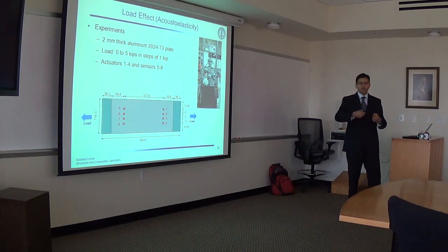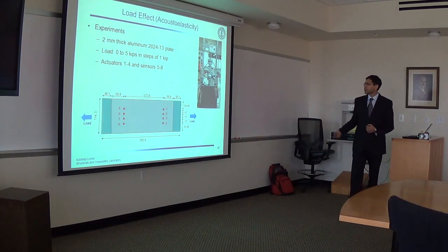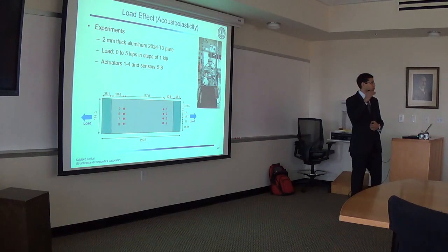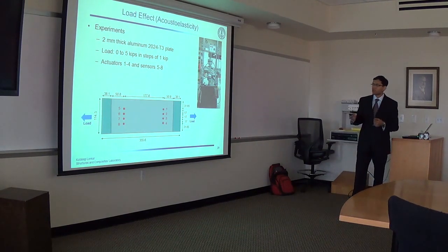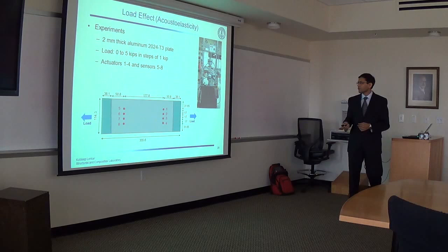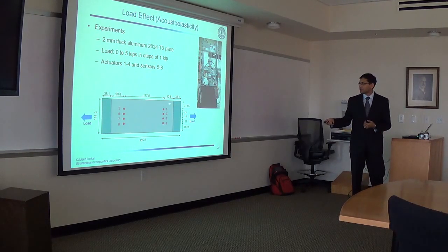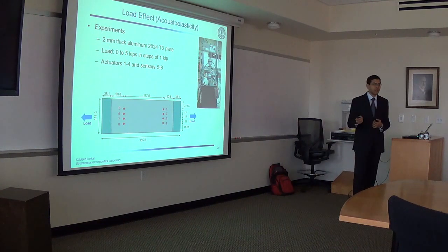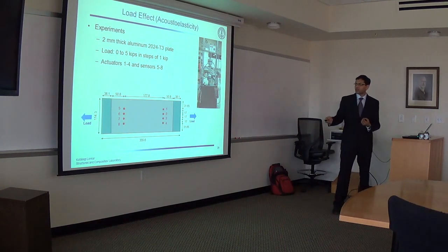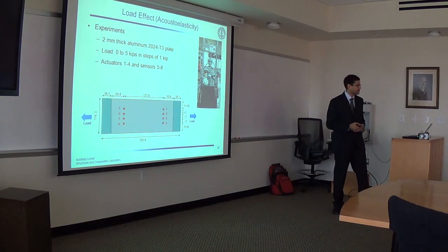The plate was loaded along the length in tension in the MTS machine. And the load was increased from 0 to 5 kips in steps of 1 kip. And at each step, we actuated actuators 1 through 4 one by one and recorded the data using sensors 5 through 8.